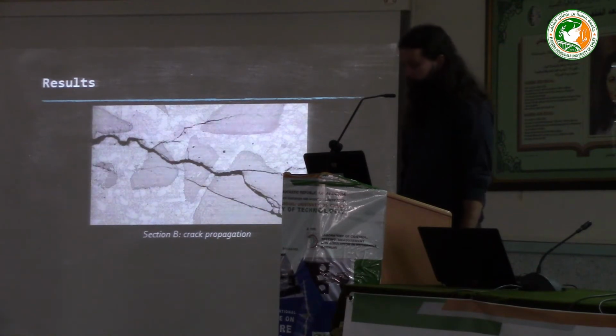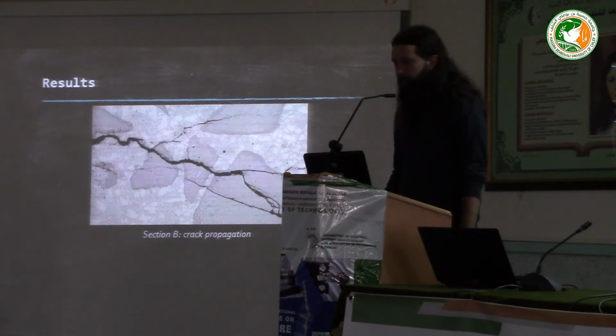Now this is another example of crack propagation from section B, where you can clearly see how the crack advances through the adjacent tungsten carbides, which also shows the point of this paper, to determine how the tungsten carbides affect the crack propagation, and here you can see the obviously negative effects that they have. On the other hand, they greatly improve the hardness, so basically the point here is to try to find a compromise between the percentage of tungsten carbides present in the welded layer, so that they can provide sufficient hardness without resulting in too many cracks. Also, as you can see in these pictures, the cracks did not propagate into the parent material in any of the 3 cases.